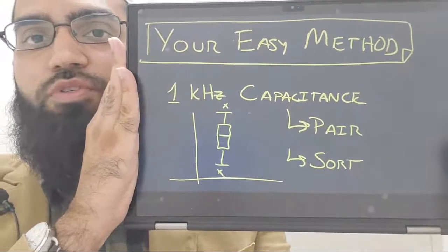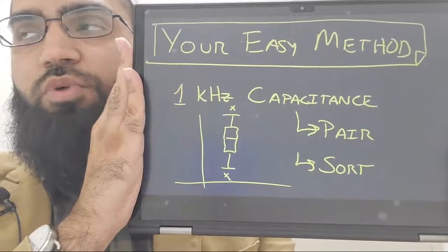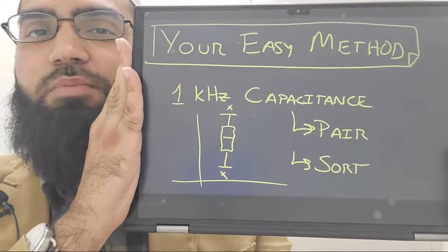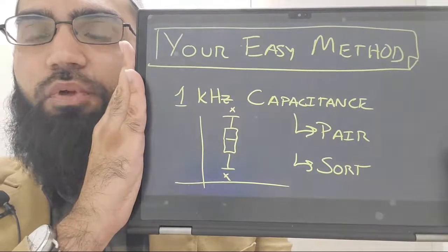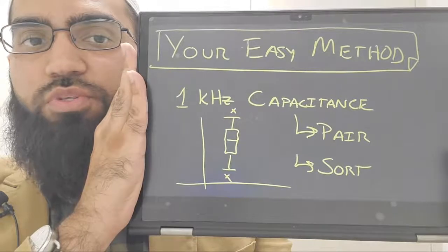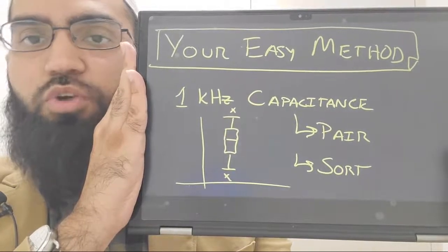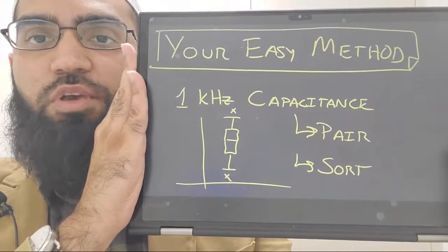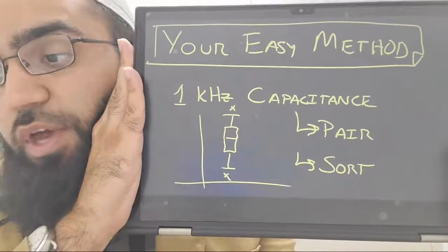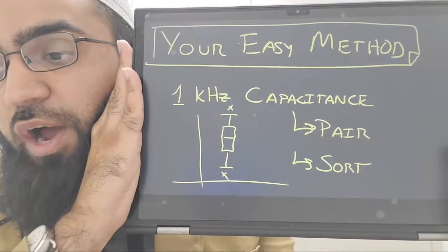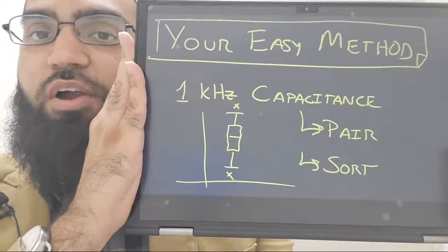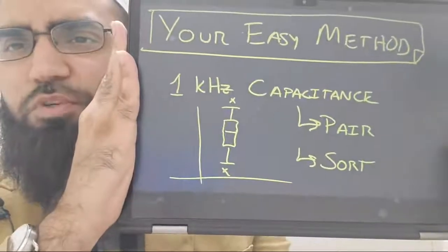Piezoelectric material properties: if you measure one of them, you're intrinsically, and I'm talking mostly about PZT, measuring the rest of them in an indirect way. Capacitance is related to the piezo charge coefficient. You'll find that if you measure the charge coefficient for 100 ceramics, let's say via the D33 meter, and you measure the 1 kilohertz capacitance, the piezos with higher capacitance will have a higher D33 value. Those aspects are related, and they'll also have a higher coupling factor for the most part.